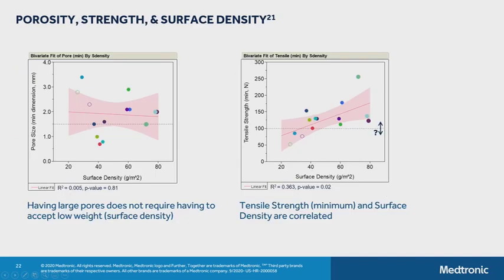Now, our team in Trevoux has mapped this out graphically. They've taken a smattering of different meshes that are commercially available. They've looked at pore size and graphed this against surface density. And they found that there was no correlation between the two. On the right, though, you can see tensile strength did have a correlation with surface density. And this sort of makes sense. The textile with more material per unit area could be stronger.